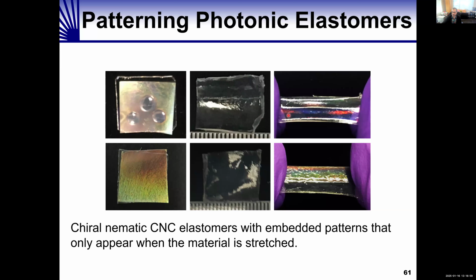In the top right, you can see the red spots where the water droplets were added to pattern it inside of a blue background. On the bottom, when you stretch it, you get a gradient of colors perpendicular to the stretching direction because of the way that we patterned this film to begin.